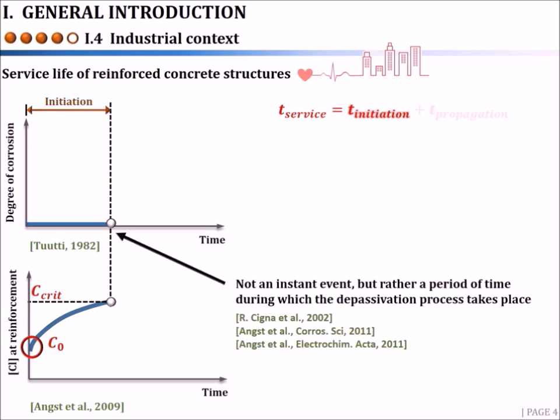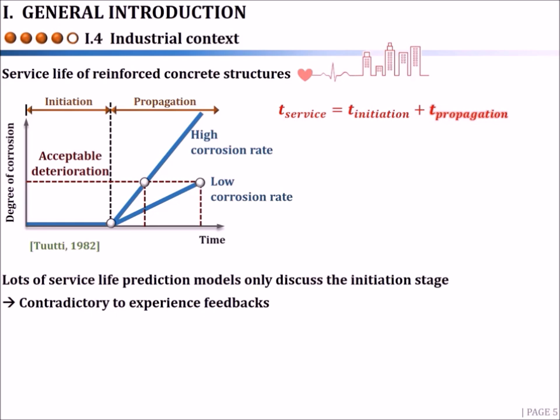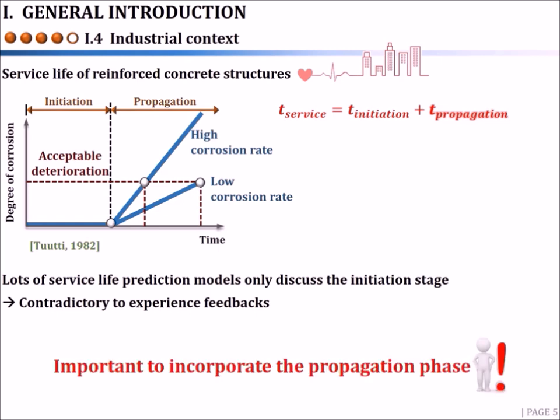The transition from initiation to propagation phase is not an instant event, but rather a period of time during which the depassivation process takes place. The propagation stage is the period after depassivation where active corrosion takes place. Lots of methods for lifetime prediction only discuss the initiation stage without including corrosion propagation, which was found to be in contradiction with experience feedbacks. Therefore, it is very important to incorporate a part of the propagation period in the lifetime of the structure.